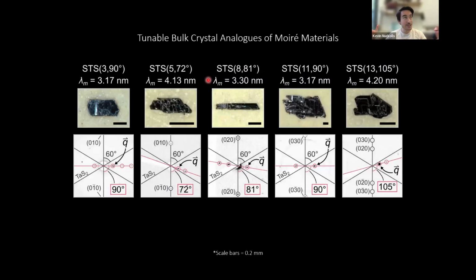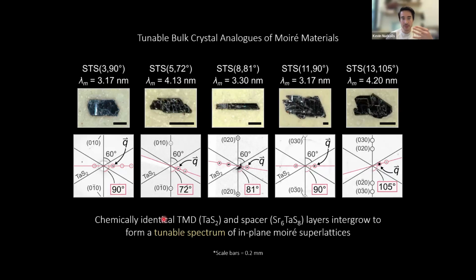So with a lot of tools in solid state chemistry, we can vary the growth profile, the temperature profiles, the starting precursor stoichiometries, and the types of catalysts to grow these crystals. We found that there are a wide variety of Moiré superlattices that all have the same stoichiometry from chemical probes like wavelength dispersive spectroscopy. They seem to stabilize a bunch of different diffraction patterns, which tells us that the Moiré superlattice is distinctly tunable in this phase diagram from about 3 nanometers to about 4.5 nanometers, in various different directions. So altogether, these compounds seem to stabilize chemically identical TMD, tantalum disulfide, and spacer, strontium-6 tantalum sulfur layers that intergrow in a wide tunable spectrum of in-plane Moiré superlattices.